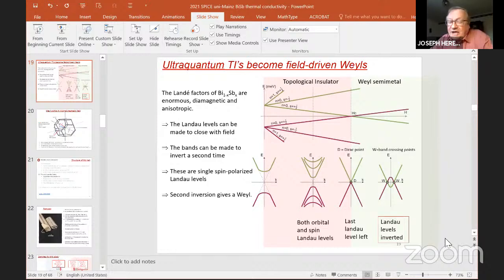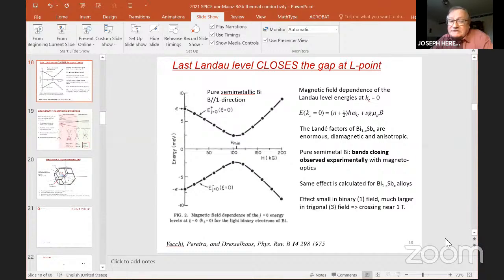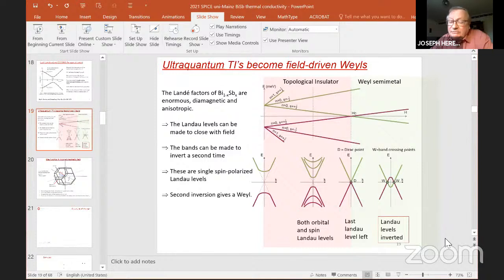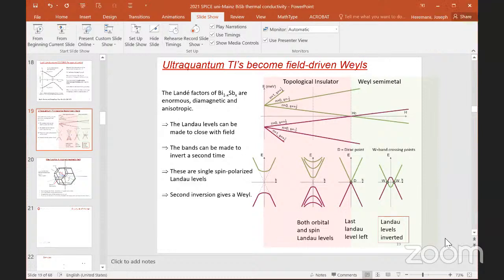Okay, so yes, you can. There are data on tantalum arsenide, and they show a very small effect, an increase in thermal conductivity with longitudinal magnetic field, but a few percent, whereas we see 300%. I don't think it's really a matter of mobility, because our data are not really mobility dependent within a factor of 100. I think what matters most is to get the chemical potential right at the Weyl point. I see. Because tantalum arsenide has all these trivial pockets. There's still some wild physics that transpires when you have the chemical potential deep in the band, but it's not nearly as clear as when you put the chemical potential at the Weyl point. I see. Okay, thank you very much.